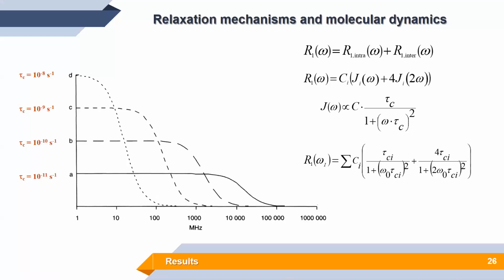We know that field cycling NMR relaxometry allows us to study nuclear relaxation processes as a function of magnetic field strength. By this, we are able to analyze the shape of the spectral density function, which contains information about the molecular motions that take place in the studied systems. It is also known that if there are any disturbances of the molecular motions, of the molecular dynamics, either because of some geometrical restrictions or interactions at the interfaces, for example at the surface of the gel matrix, it will be reflected in the relaxation behavior.